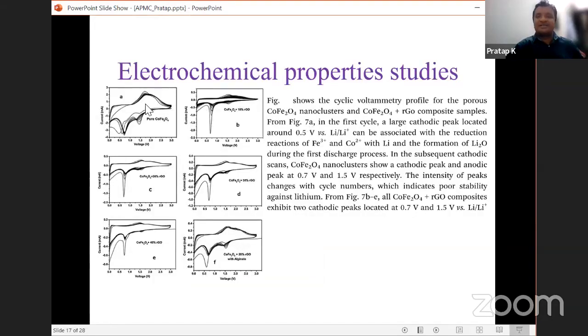So we have studied the electrochemical properties. The electrochemical properties means we made it into a coin cell. You might have seen coin cells, right? Maybe in your batteries or in toys, there will be coin cells, like CR2032 coin cells. So we prepared a coin cell and we checked the electrochemical properties using cyclic voltammetry. This is for pure cobalt ferrite. This is for cobalt ferrite with 10% RGO. This is for cobalt ferrite with 20% RGO. This is cobalt ferrite with 30% RGO. This is cobalt ferrite with 40% RGO.